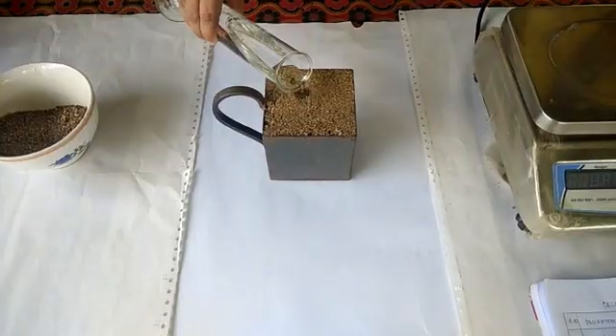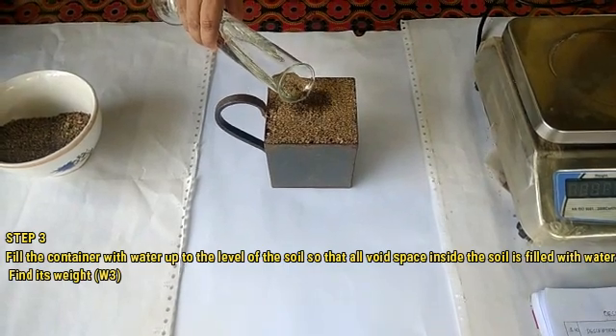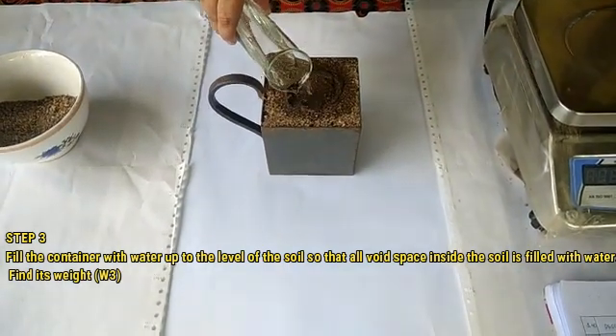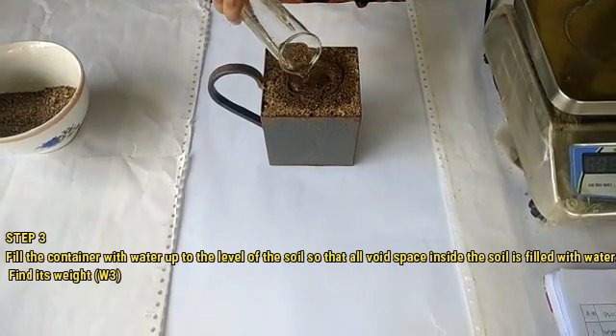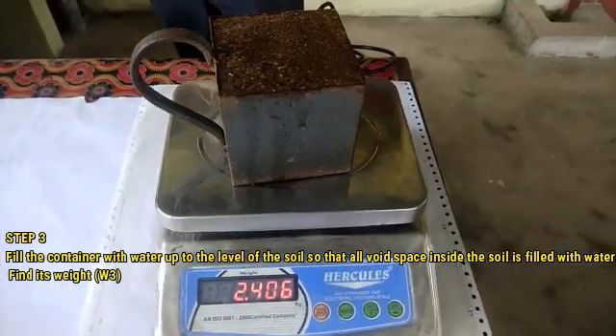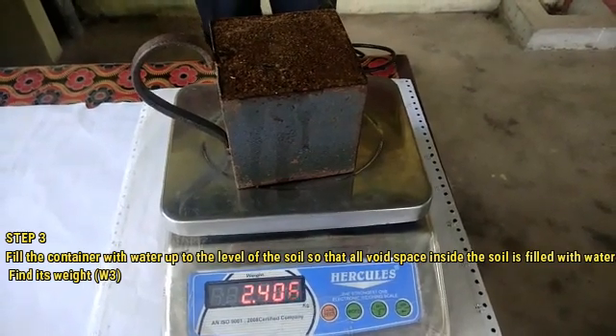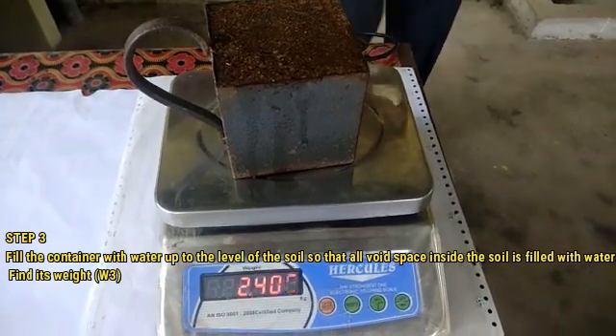Again, carefully add water to the sample taken in the container till all the sand voids are completely filled with water. Now, note its weight as W3. Note its weight as 2.406 kilogram, 2406 gram.